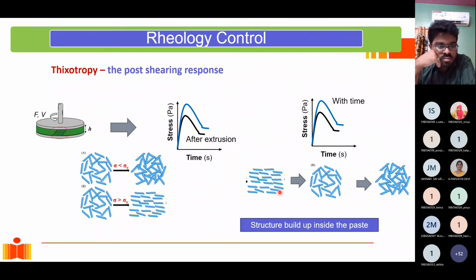And in the at rest condition, what happens is that again, the structure starts building up inside. So you see, when the material was flowing, all the particles were nicely aligned. Then when it comes to rest again, the particles become randomly oriented. So when the particles become randomly oriented, again, you'll have resistance to flow. That means internal structure starts building up, and now the material will tend to keep its shape because it takes some effort to overcome this structure. And with time, if I wait, the structure again densifies and the resistance to flow starts increasing. And that resistance to flow post-shearing response is what we call thixotropy.